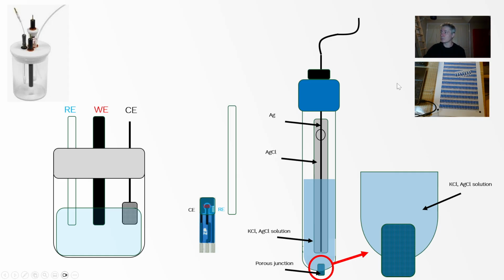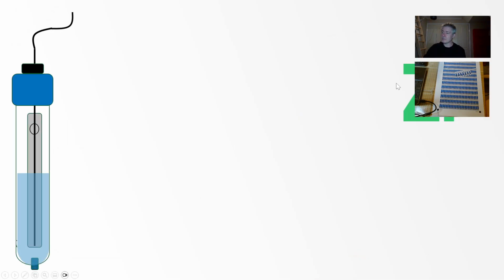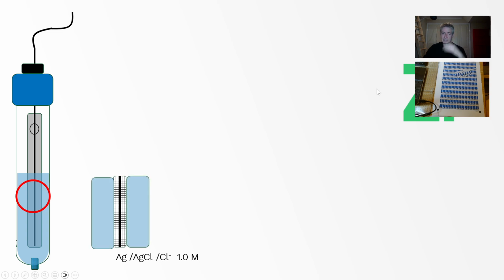So we have our potassium chloride solution, and we're protecting it from the rest of the experiment through this porous junction. Now if we zoom in on this, we have our silver wire, we have our silver chloride on the edges of it as well, sitting in a solution. Let's say that solution was 1.0 molar. So we've got silver wire covered in silver chloride in a 1 molar chloride solution. That will have a potential that's governed by the Nernst equation, where we say the potential for that reference electrode is its standard potential, which for silver chloride under standard conditions is 0.222 volts, minus 59 times the log of the chloride concentration.